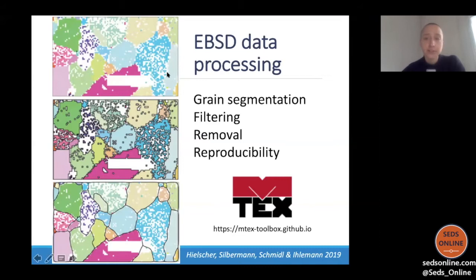I really want to stress here, because this is going to be important for later in this talk, that what we define as individual grains or crystallites, scattering domains, which basically means areas which diffract in the same way, can be very arbitrary. It is probably not very arbitrary here, although you can see that if you just wanted to join the fields of similarly oriented pixels, you might end up with a lot of spurious small grains that are not really grains. It's just there was not a lot of signal in this area. And this is where we need good algorithms and also good understanding of the minerals we're looking at to identify grains in a meaningful way.